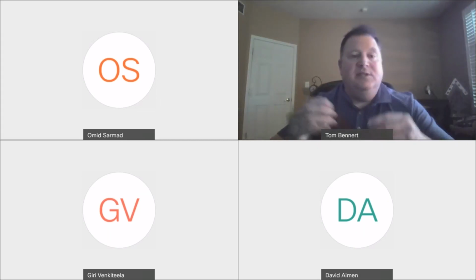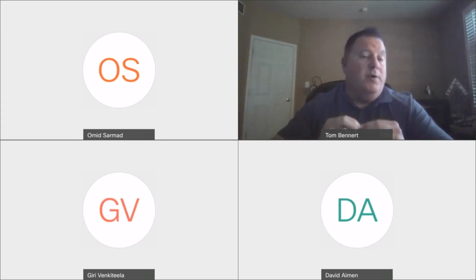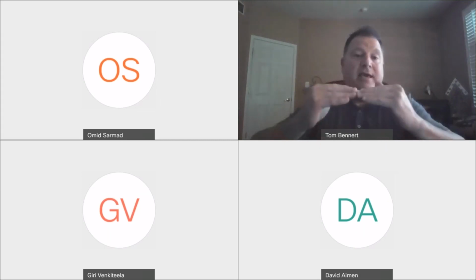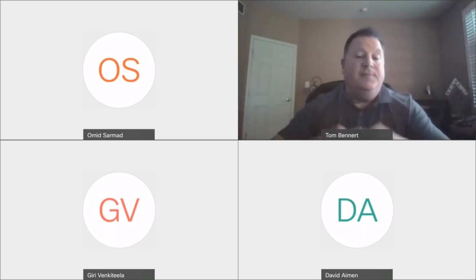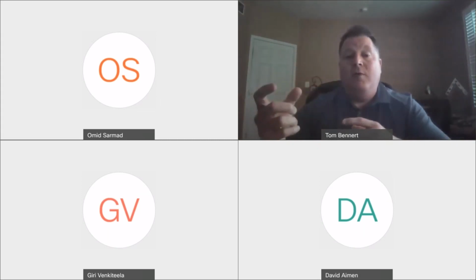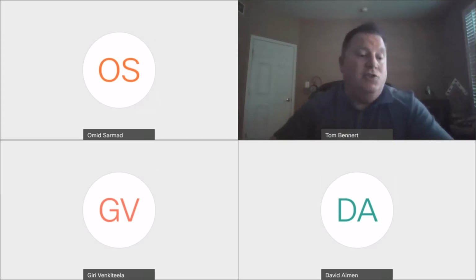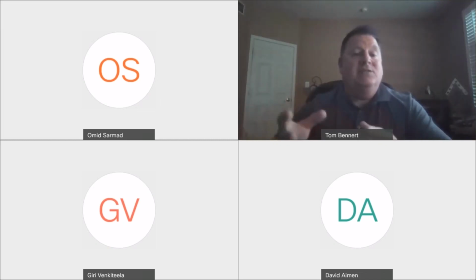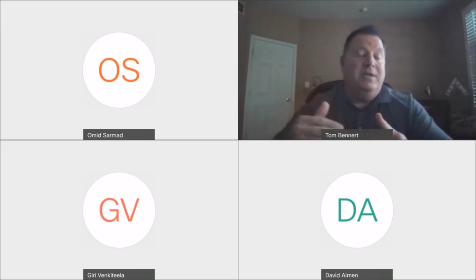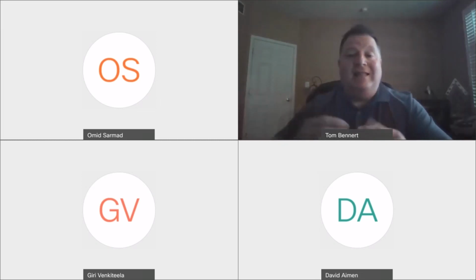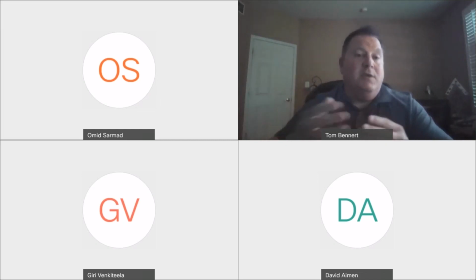One of the things that happens is embedment depth of that aggregate is very important. So you don't want it to be embedded too deep, where the aggregate is almost drowning in the epoxy. And you don't want it too shallow, where it can actually pull out very easily during traffic. So what they say in those specifications about monitoring those first couple of years for friction is to look for those things, to make sure that your embedment depth wasn't too deep, where you're not getting the friction you were hoping for, or vice versa, that the embedment depth wasn't enough and now these aggregates are starting to pull out in traffic. So that's what they were looking for.